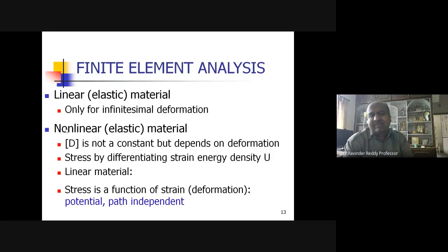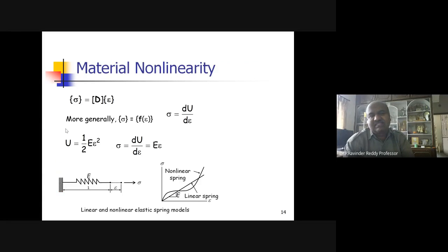The stress, by differentiating strain energy density, you can use the linear material, you can use the nonlinear material. Then stress is a function of strain, the deformation dependent in case of nonlinear geometry. And you can model potential and path independent analysis. Typically, when you see the relationship stress versus strain, there is going to be a material matrix. This could be linear, this could be nonlinear. So if it is nonlinear, there is a functional which we are going to use, then the material model and geometric model are going to be nonlinear. In general, if you want stress in terms of energy, du by d epsilon, and energy you can write as half of E epsilon square, when you have a relation between stress and strain with Young's modulus.